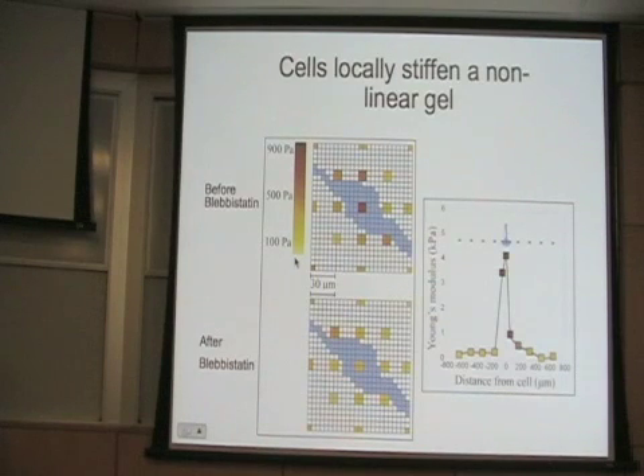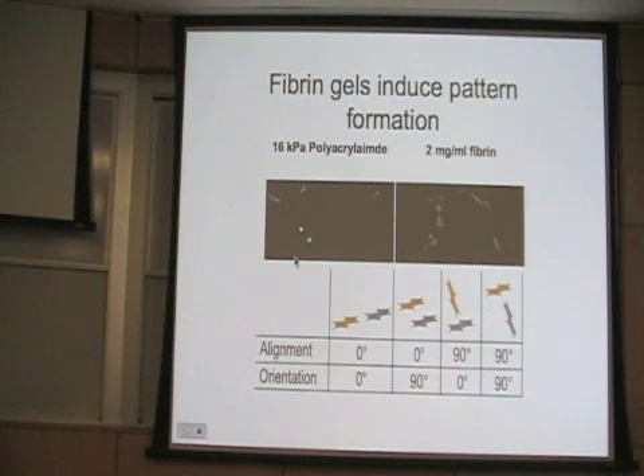So the cell, by putting in contractions, is not only transmitting tension along its matrix, it's also locally stiffening the matrix. So a cell anywhere in the zone that a neighboring cell has been pulling feels a stiffer substrate than it does far away. So this has at least one consequence that's related to cells signaling to each other, or cells mechanically sensing each other. It's something we don't see very well in linear polyacrylamide gels of the same elastic modulus; we see much better alignment of the long axes of cells when they're on these strain stiffening fibrin gels with these very long range strain fields.